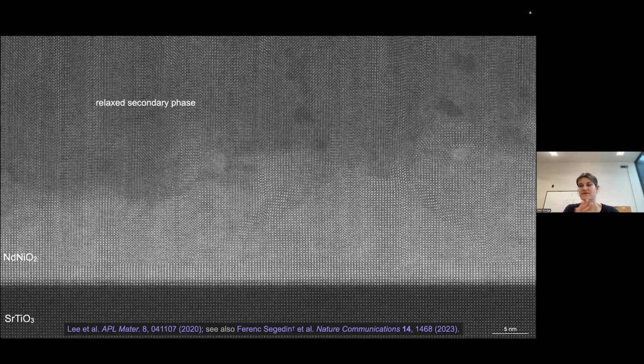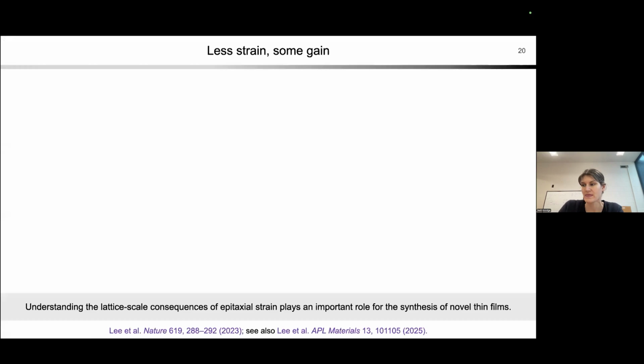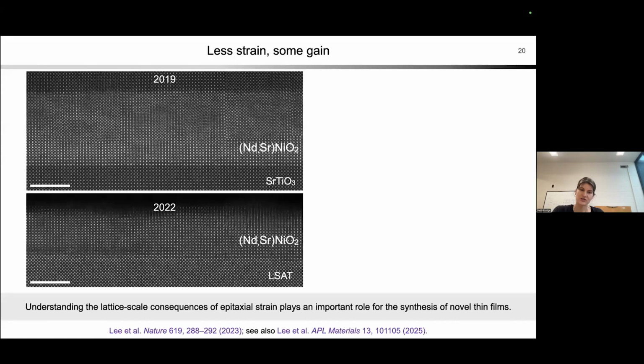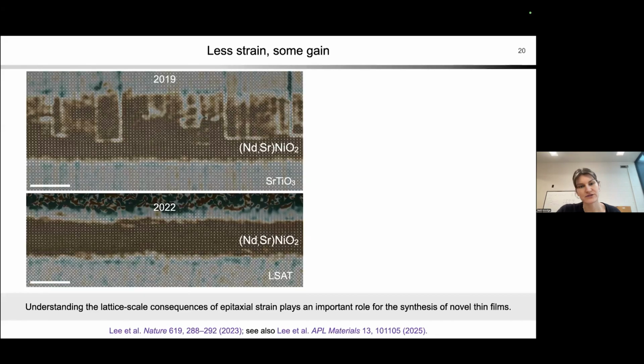So there's this very careful threading the needle, a Goldilocks zone, to get a strain which is in some cases useful for the material, but not so much that you can't stabilize high quality materials. Again, that's an extreme example, but there are more subtle cases. We can see this very clearly in the electron microscope. Here I'm mapping out these defect phases, which form as a function of strain. Comparing two different films from about 3 years apart, the one on the top is quite a bit messier than the one on the bottom.